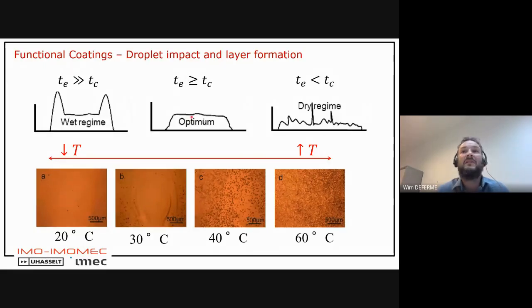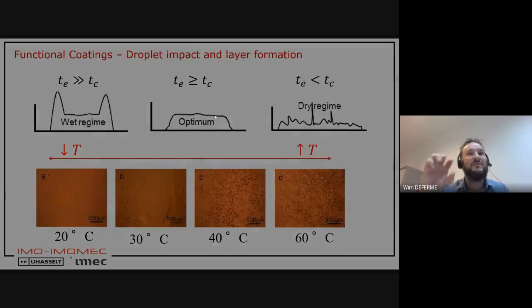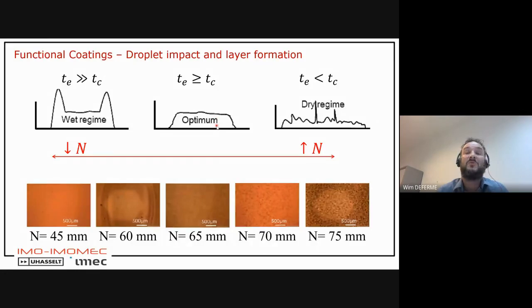And if it evaporates completely, then you arrive in the dry regime, and you get this, because you have a lot of nanoparticles deposited all over the place. But of course, if your droplet is still wet, due to the coffee ring effect, most of your nanoparticles will move towards the edges because of the specific evaporation of your solvents. So you also have to play with optimized solvents, co-solvent systems, to finally arrive at what they call the optimum, where the distance between the nozzle and the substrate is optimized. The distance here, you see, going to 60, 65 millimeters, 6.5 centimeters, gives a more optimal final result.